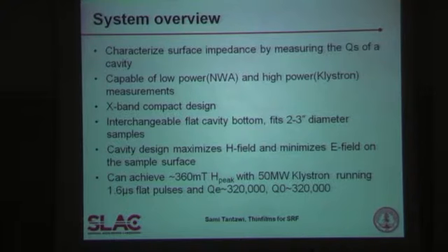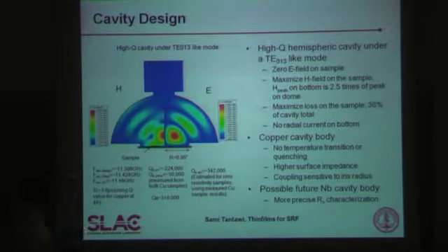So the system is basically composed of real copper, and the basic idea, this was the original idea of the whole system, is that we characterize the samples with a very short pulse from a very high power system, and in that case all thermal effects and everything in the system is not a factor in determining the quenching field. Well, it turns out that this cannot be done. It's far away from reality. But without further ado, this is the basic cavity structure.